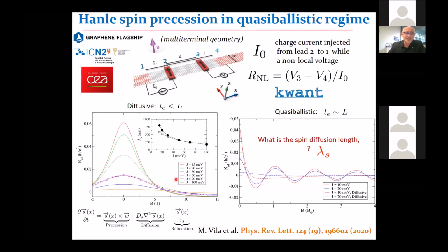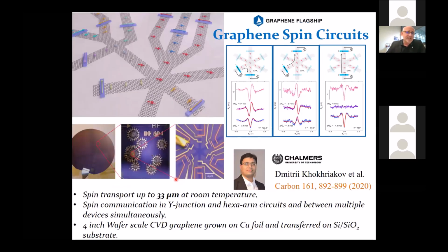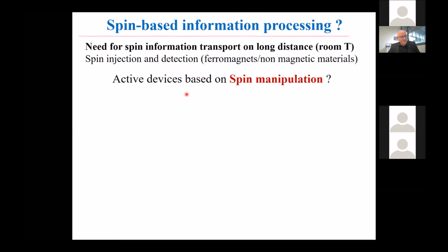Now we have, of course, the capability with these so long spin diffusion lengths to start working on very complex architectures. This is an example from our colleague from Chalmers, Saroj Dash, where he demonstrated that the non-local spin signal can be detected in different branches, and you can start to play at will by using lithography, and so you can start to make some kind of complex spin information analysis because we have this so long spin diffusion length. So now, beyond transporting spin information, we want to manipulate this information.